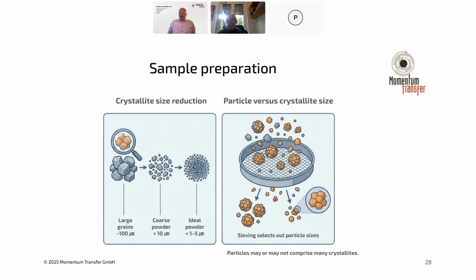Another thing to keep in mind is that the particle size and the crystallite size are two slightly different things. Particle size is really the aggregate clusters of material in your sample. They could be a single crystal, but they could also be a clump of many smaller crystals. In that case, it's no problem, because what the X-rays see is actually the coherent scattering domains, which is the length over which the structure scatters the X-rays coherently, which can be the crystallite size, but can typically be a bit less if there are defects in the material, which is certainly the case for many natural materials.